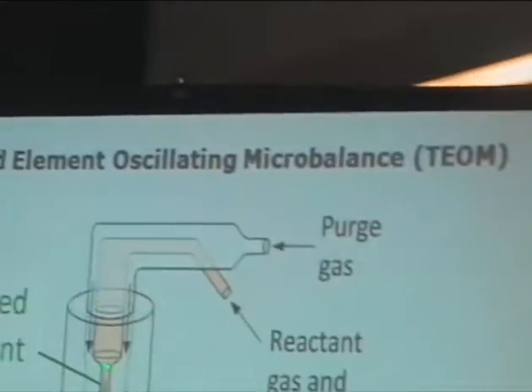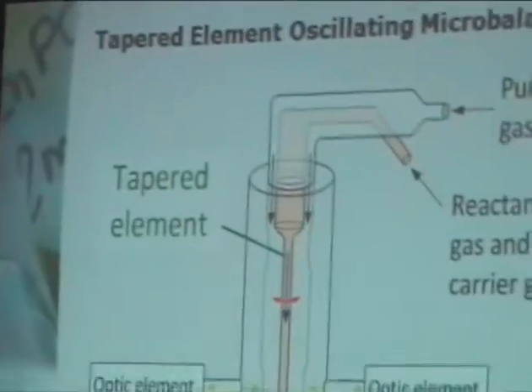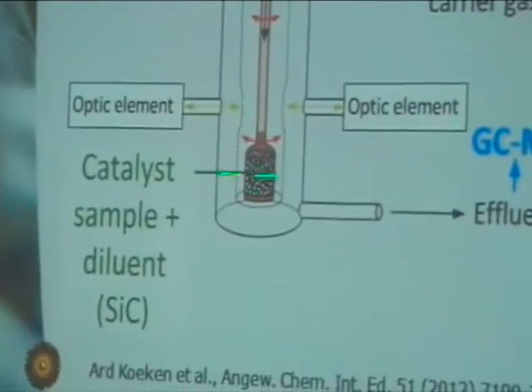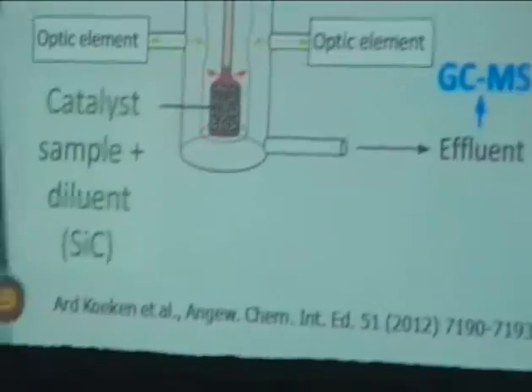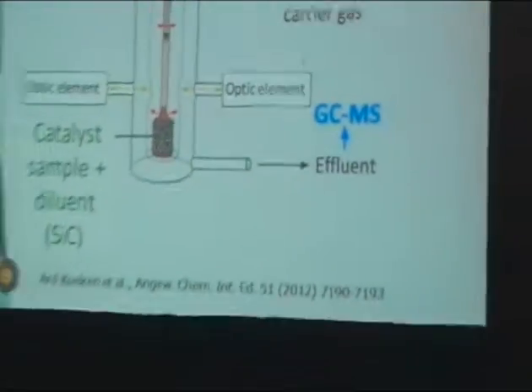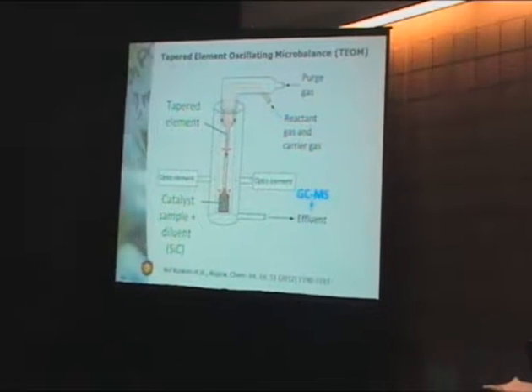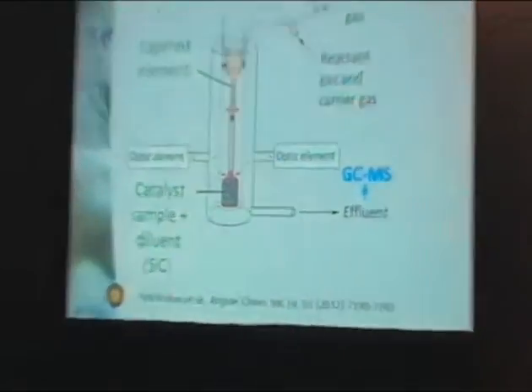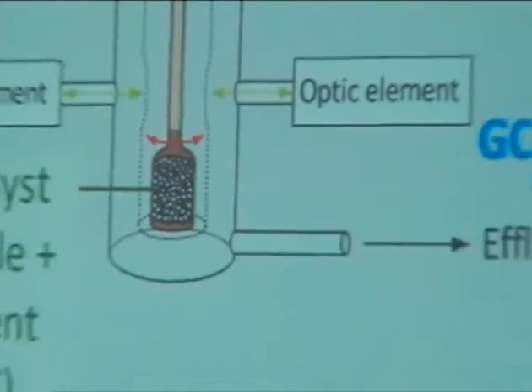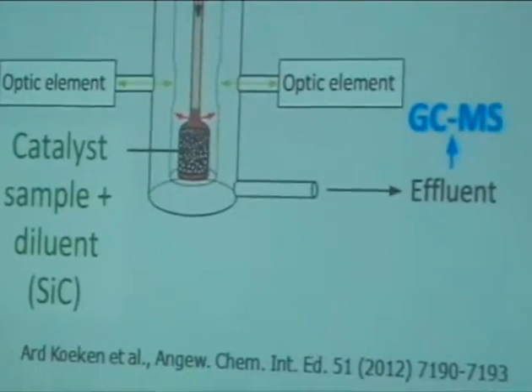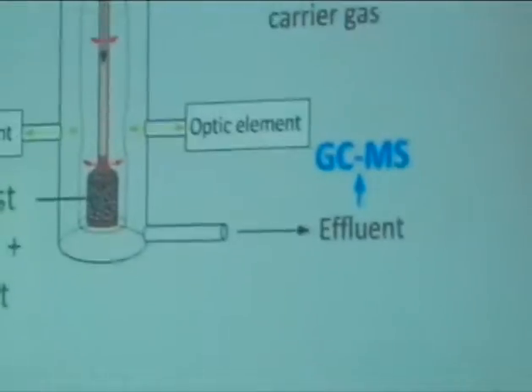Now what we did in a so-called tapered element oscillating microbalance, where we have the possibility to operate at 20 bar under real plug flow conditions, so we have a catalyst bed in a hollow rod, and the synthesis gas can flow through the catalyst bed under plug flow conditions. We can measure very accurately the mass of our sample under a full catalysis experiment. We have published this recently to be applied for FTO. Again, I have to mention here the work of Du Chen and Anders Holmen, who did extensive carbon growth studies, carbon nanofiber growth studies, on nickel catalysts with such a system.